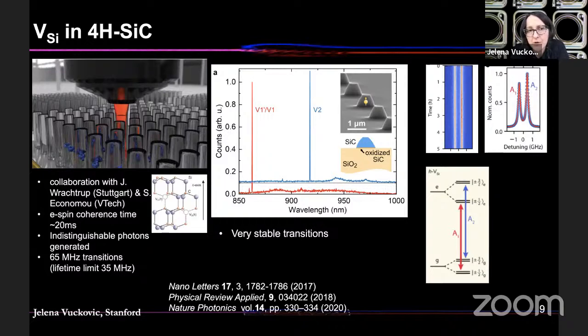People have measured an electron spin coherence time for the silicon vacancy of 20 milliseconds. Generation of indistinguishable photons has also been demonstrated in Stuttgart by our collaborators. And the transitions are very narrow and close to the lifetime limit. We also demonstrated that these color centers have extremely good stability. Here you see transitions over 5-hour timescales, but we have measured this over even 10 hours or more. So they're very stable, and they have excellent optical and coherence properties.